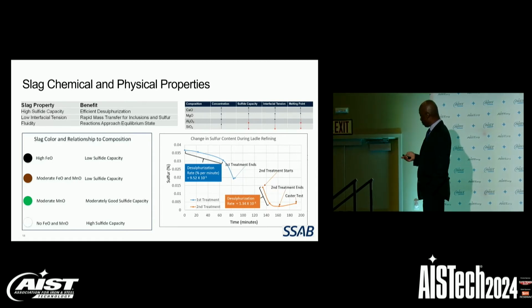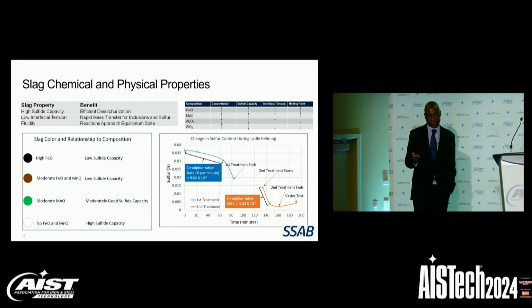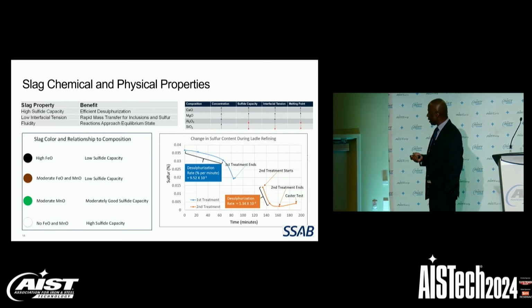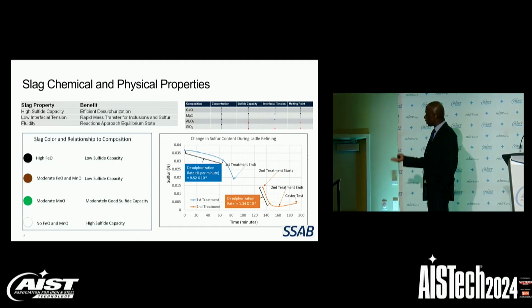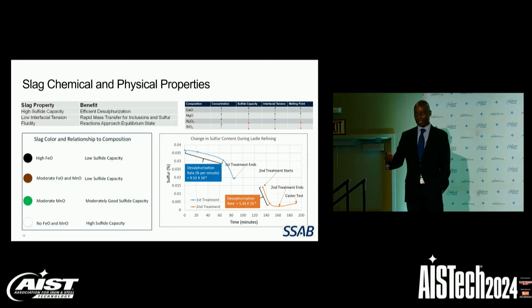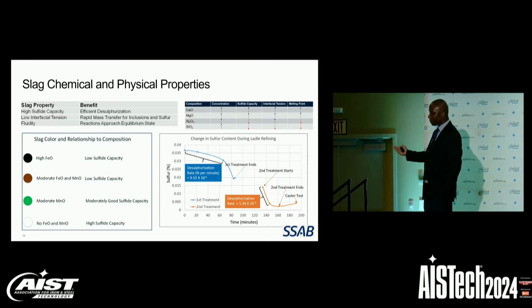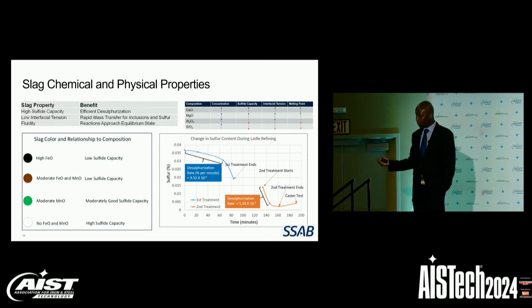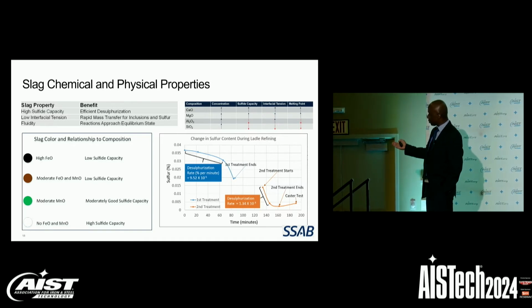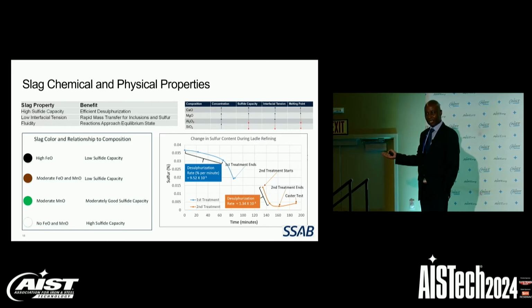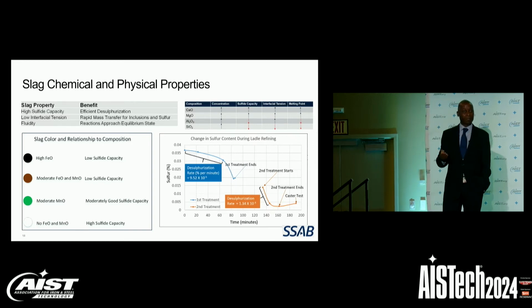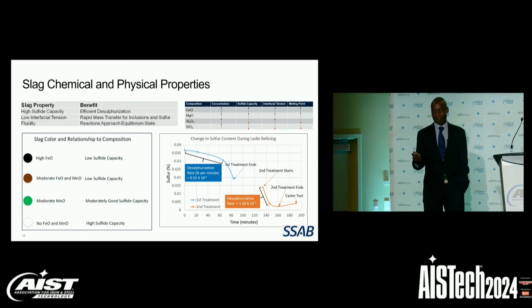What we're showing here on the chart is evolution of sulfur during refining of the steel at the ladle metallurgy station. For the first 60 minutes of refining, the sulfur removal rate was very low. The operators had to rake off the original slag, make new slag, before they had rapid desulfurization in that particular heat. But as you can see, that heat took us almost 200 minutes to process at the ladle metallurgy station, compared to typical 30 to 45 minutes of refining.